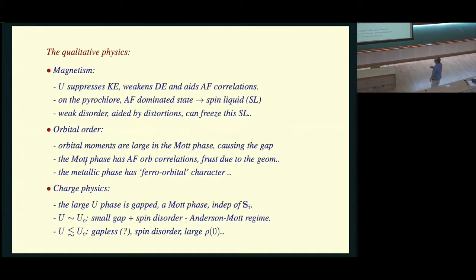Longish text, it says the U and the JAF conspire. U suppresses kinetic energy, inhibits double exchange, aids antiferro correlations if you wish. So the ferromagnetism is aided by the Hund's coupling and kinetic energy, but the U and the JAF are sort of opponents of that. So either if you go to large U or go to materials with an effective large JAF, the ferromagnetic tendency is suppressed in favor of the spin liquid, spin glass character.